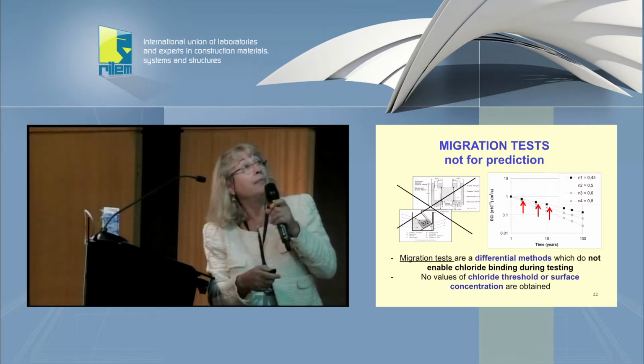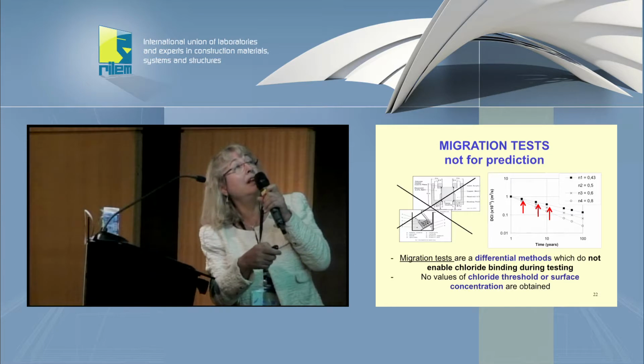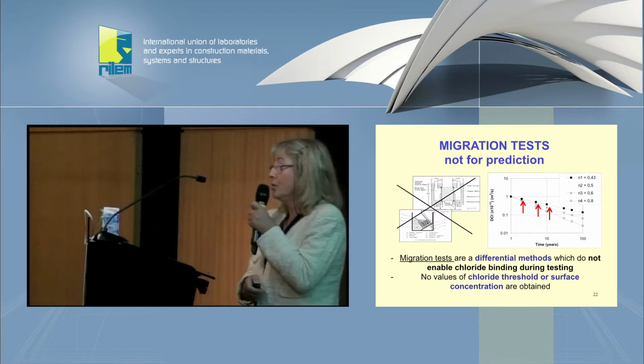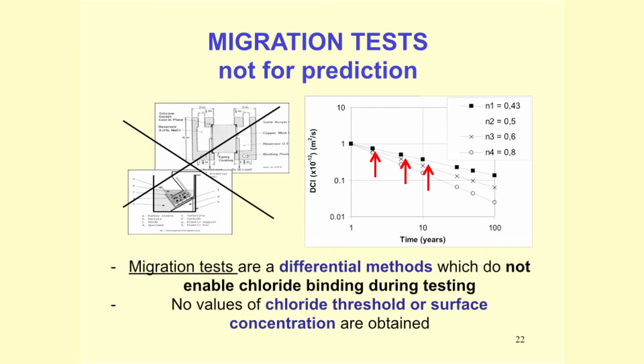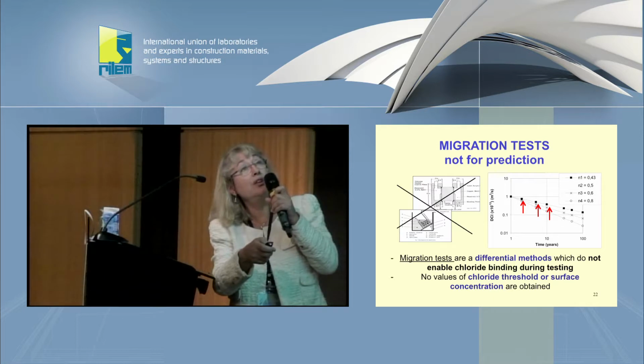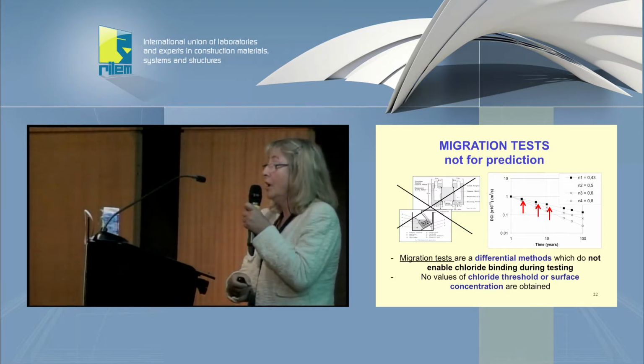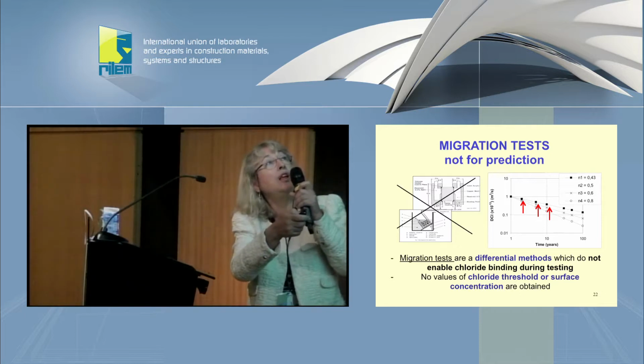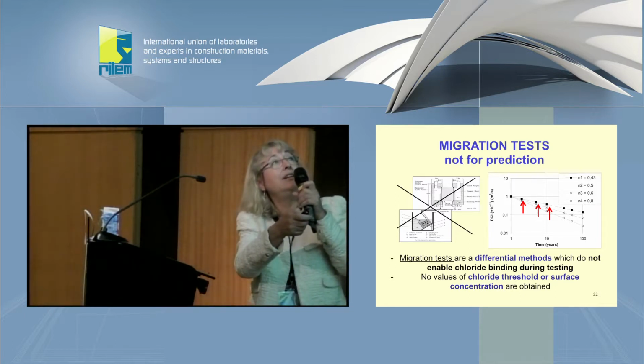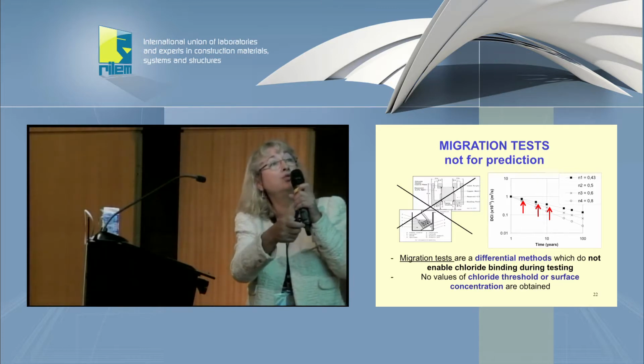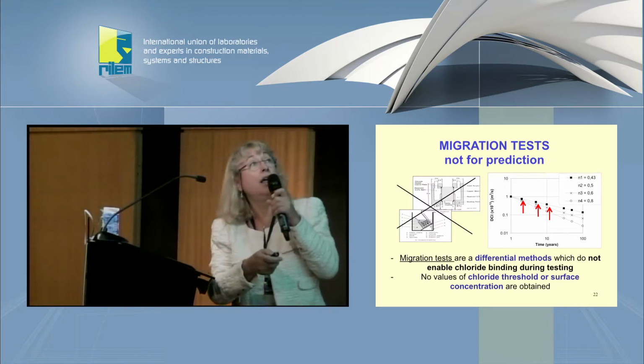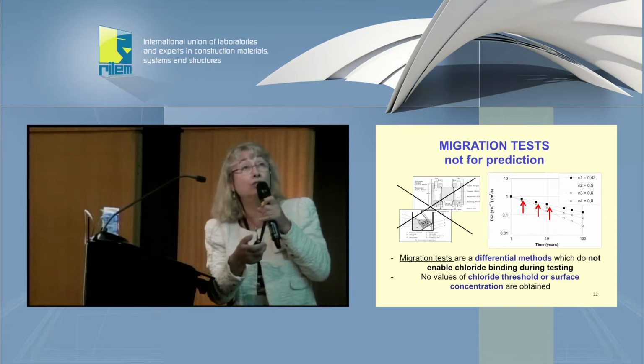I am against using the accelerated test, whatever it is, if we go to the aging factor, because in this case the concrete is aging out of the salt solution. You just leave the concrete, and after a certain moment you measure, because if it is in contact with the salt, you cannot use these methods. Maybe the one on the coulombs, but you are removing the chlorides that have been entering in contact with the salt water. In that case, you cannot use these methods for aging, and aging is the controlling parameter.